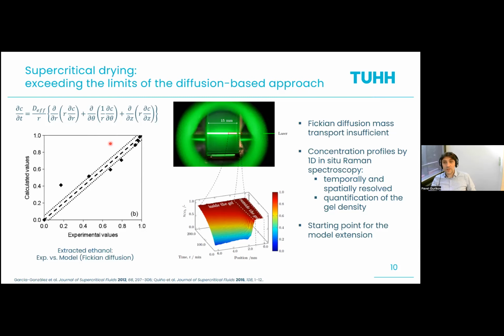And as you see, and that's very well known in the literature, in many cases during the process you are going to be off. Sometimes you overestimate, sometimes you underestimate how much solvent you extract. And then of course it does matter, because you want to bring the drying to the very end. You want to extract as much solvent as possible. So obviously this type of equation and this type of description is not complete. It is intrinsically incomplete to give you a correct answer.